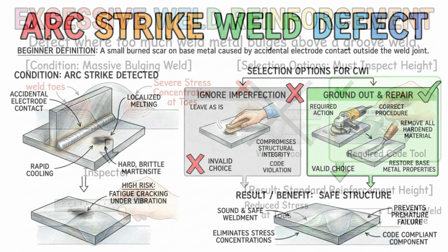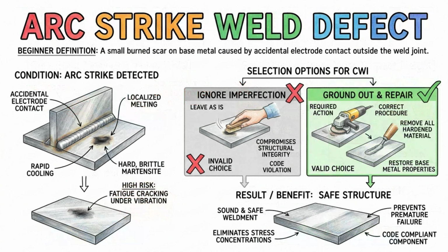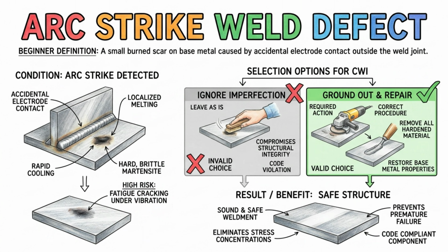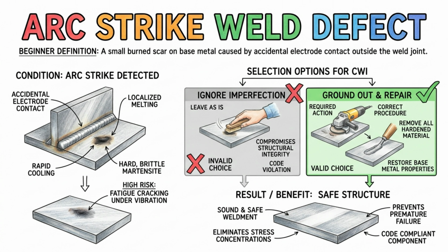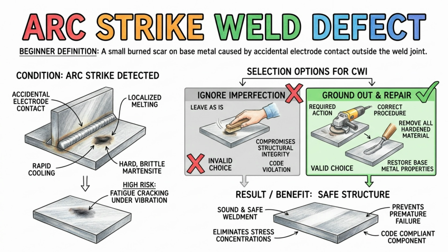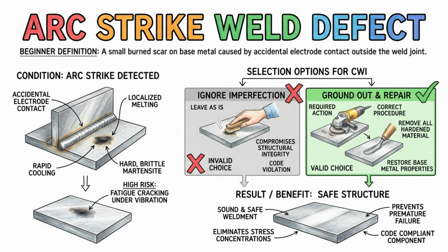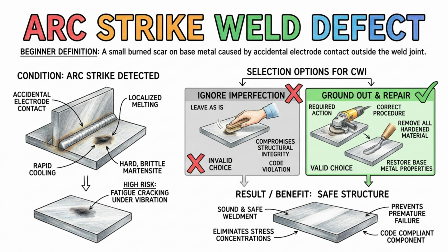Arc strikes are another subtle defect that inspectors frequently catch outside the actual joint area. A welder commits an arc strike when they accidentally brush their electrode against the clean base metal outside the weld zone, leaving a small burn scar. This localized spot melts instantly and cools rapidly into a hard, brittle patch of martensite that can easily start a fatigue crack under vibration. For structural components, you must check the surrounding plates for stray arc strikes and require them to be safely ground out and repaired.